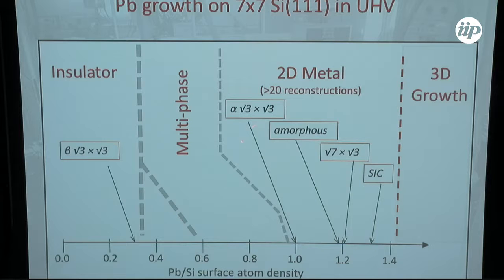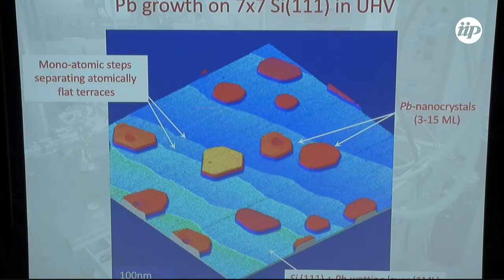And then you can isolate different phases. One that you obtain immediately if you just deposit one monolayer is amorphous. But you can also have some crystalline phases, reported here as alpha, square root 3 by square root 3, square root 7 by square root 3, etc., which correspond to the unit cell. These numbers correspond to the size of the unit cell in x and y direction with respect to the unit cell of the underlying silicon. Okay. If you continue to deposit, as I showed you before, you get 3D growth, and this 3D growth gives you these islands.